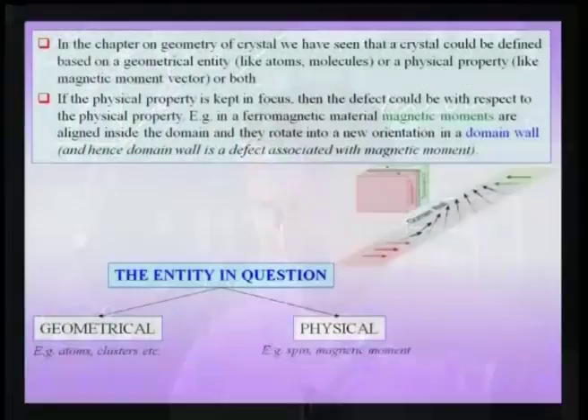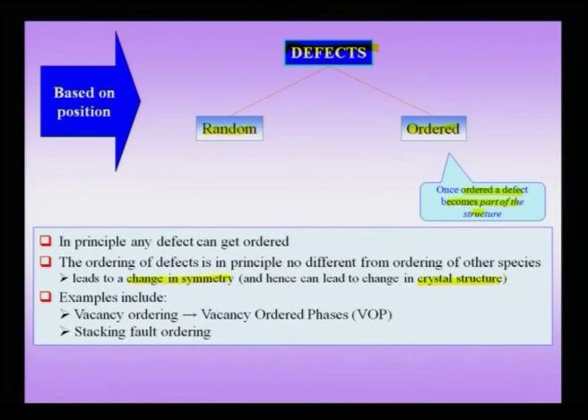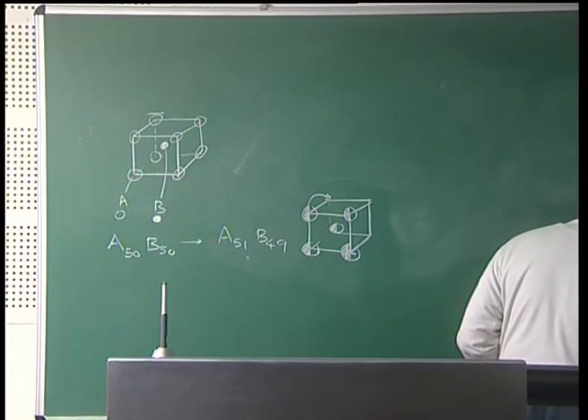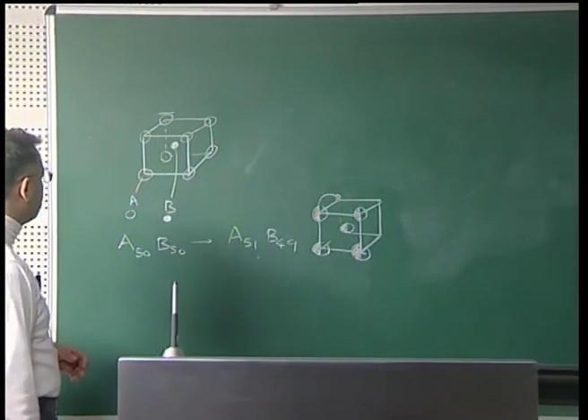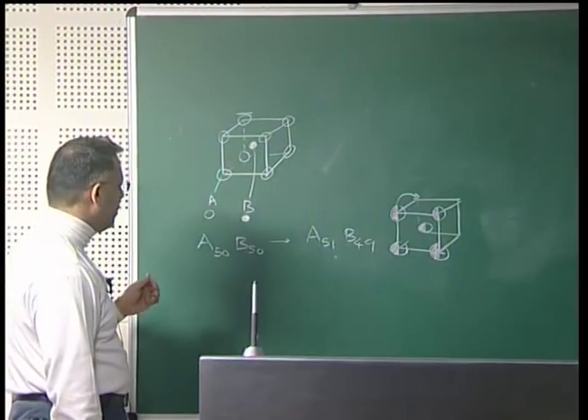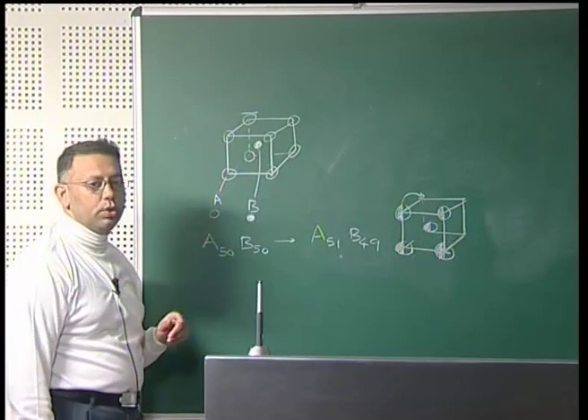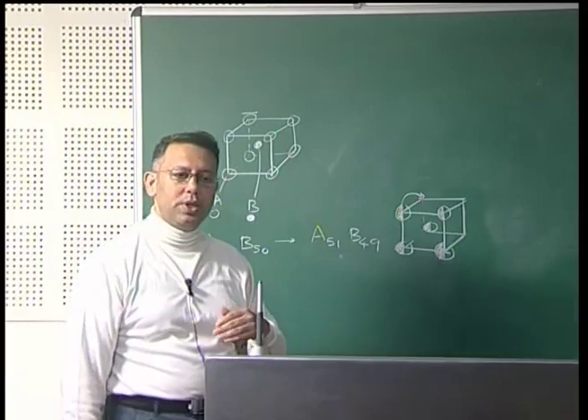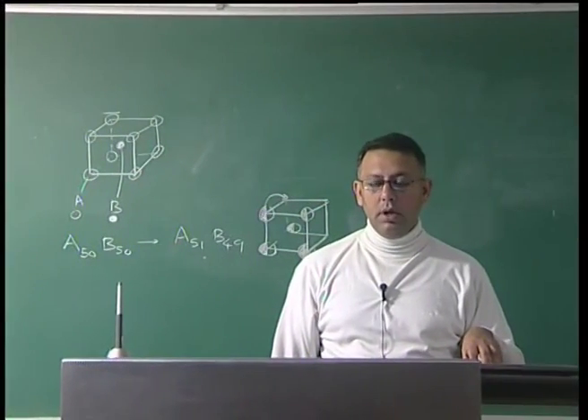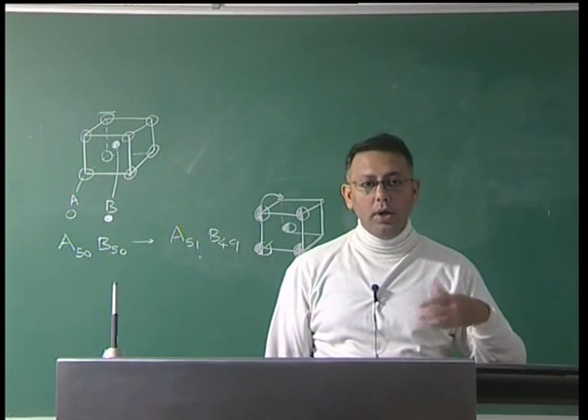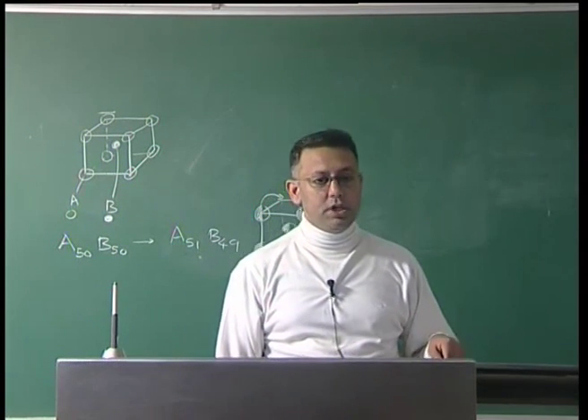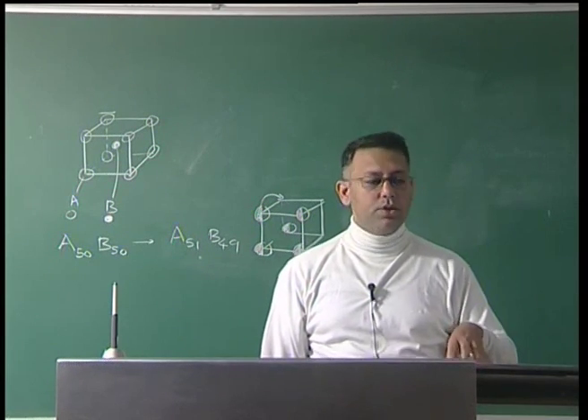If vacancies or stacking faults — defects within the crystal — get ordered, they have a more profound influence on the very definition of the crystal itself. Consider the AB kind of structure: vacancies in the B sub-lattice, introduced due to off-stoichiometry, are localized to that sub-lattice and are ordered within it. To form a vacancy-ordered phase, the vacancies must be positionally ordered even within the sub-lattice.